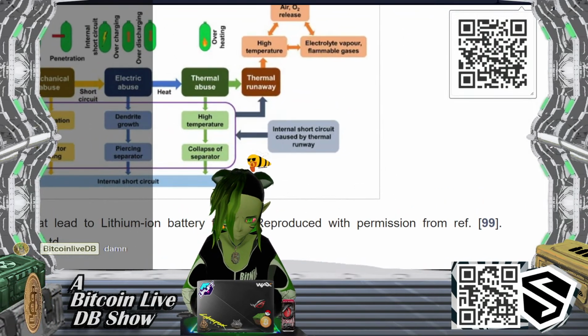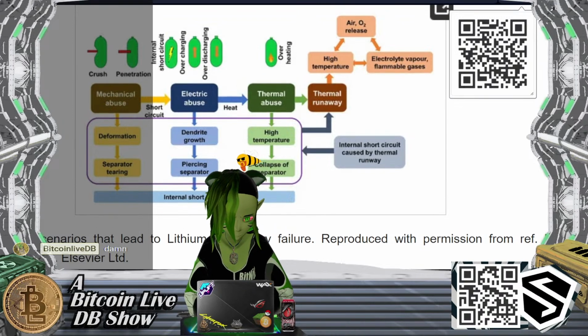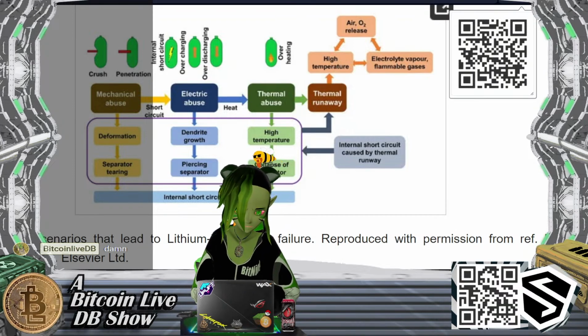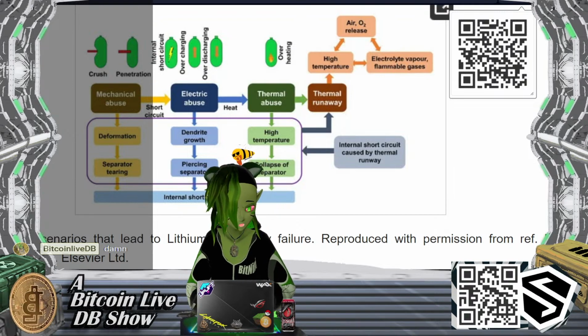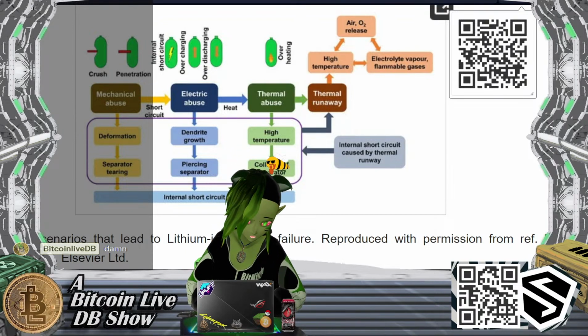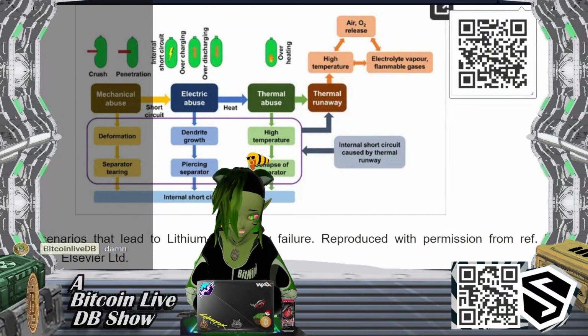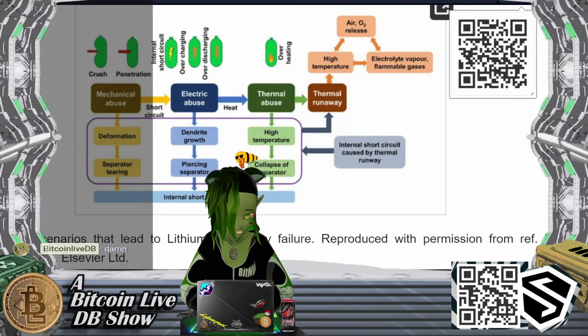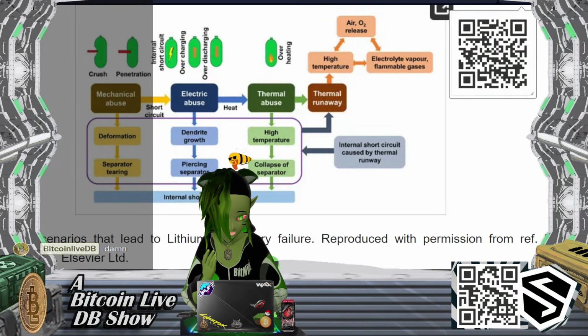So basically, this shows right here some kind of crush to the outer shell, a penetration to the shell, internal short circuit, overcharging, and over discharging. Also, anything that can cause overheating, including the thermal runaway thing. So the idea here is if there's any kind of mechanical abuse, internal short circuit. If there is any kind of electrical abuse, internal short circuit. If there's any kind of thermal abuse, internal short circuit.